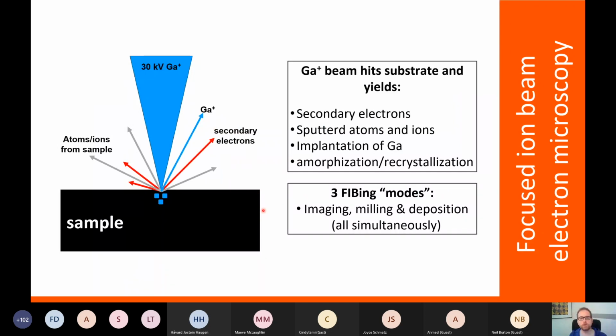So let's have a look at what happens when not electrons hit the sample, but when ions, and in this specific case gallium ions, hit a sample or a substrate. So very similar drawing as I've shown you just a minute ago. Here now we have an ion beam hitting the sample, and we have numerous interactions. We can also have secondary electrons that emerge from this ion matter interaction that should also show you topography. But we can sputter away atoms and ions, so we can cut into the sample,